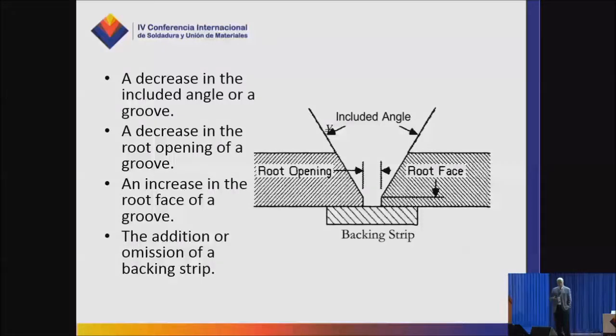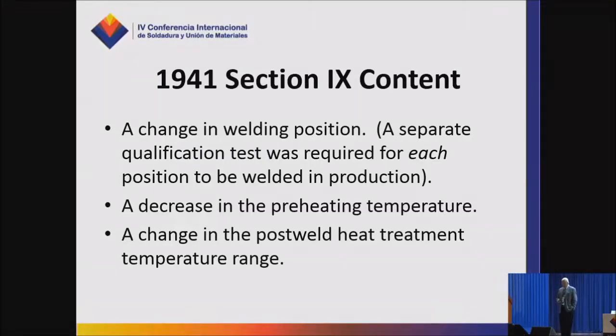These are not variables today. A change in welding position. A separate qualification test had to be done for each position, and that included the flat position. So if you were going to weld overhead, you had to qualify the procedure overhead. If you were going to weld vertically, you had to qualify it vertically. Going to weld horizontally, you had to qualify the procedure in the horizontal position.